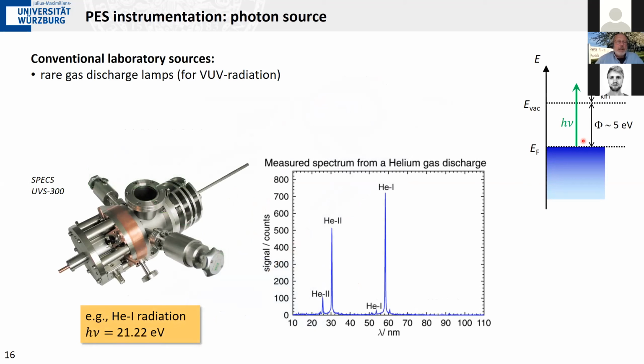So we need photons of the order of 20 to 40 electron volts, typically, in order to map out valence bands and band structures. And that's called vacuum ultraviolet radiation. Vacuum because this energy range can only be transmitted in vacuum. Any gas would absorb this radiation right away.